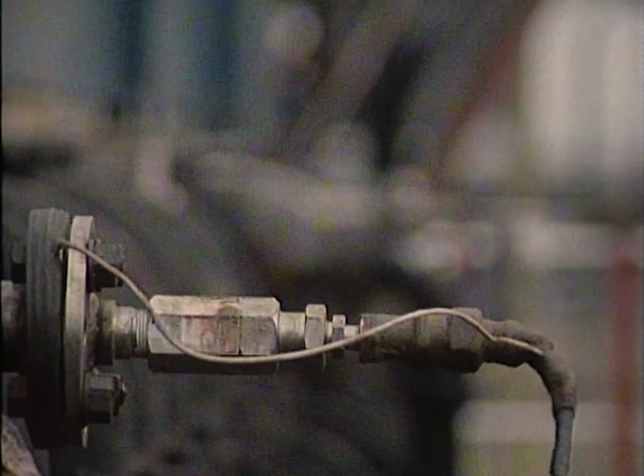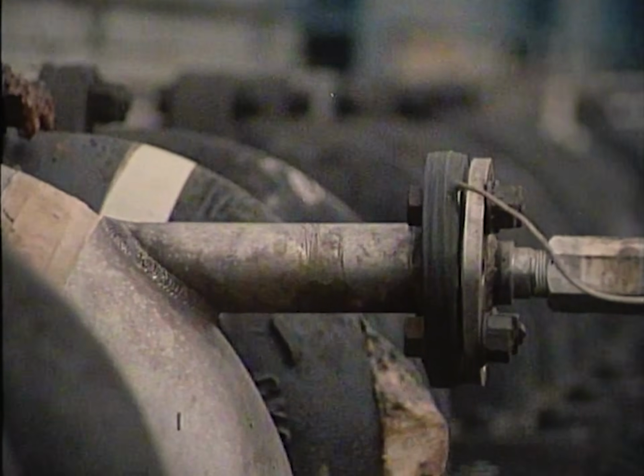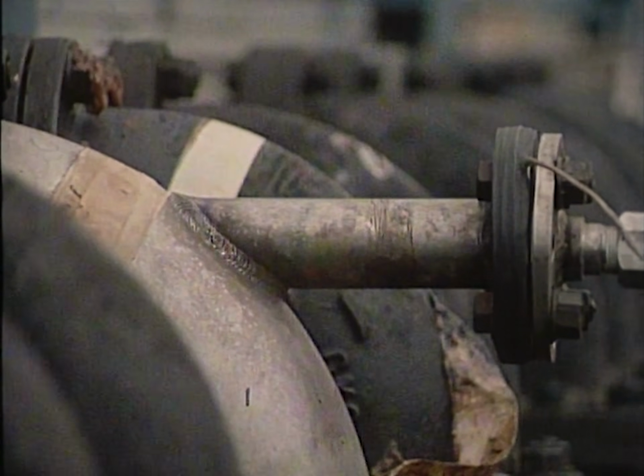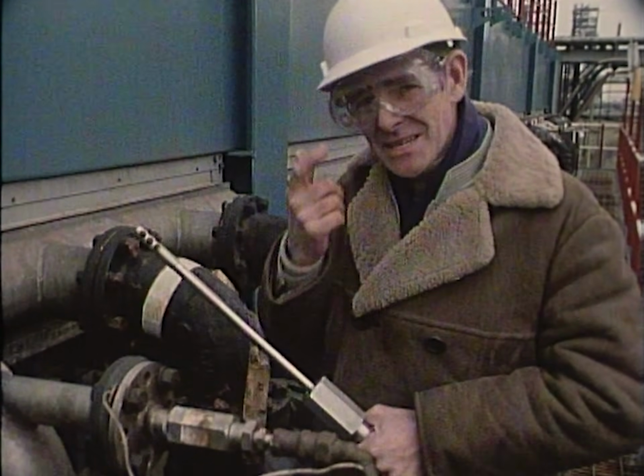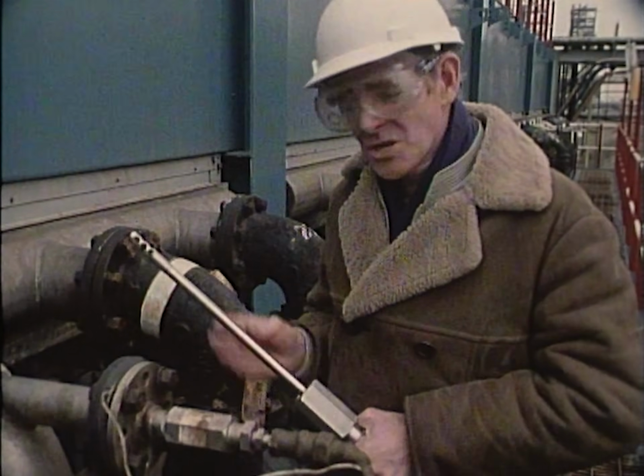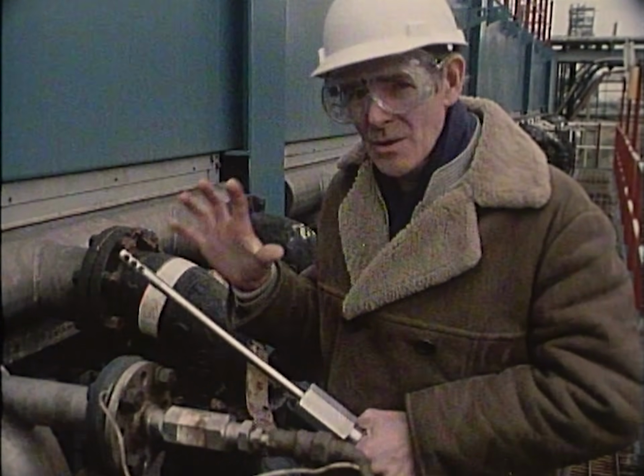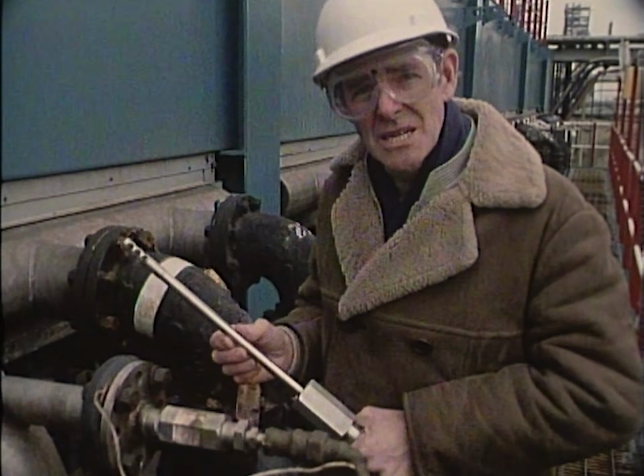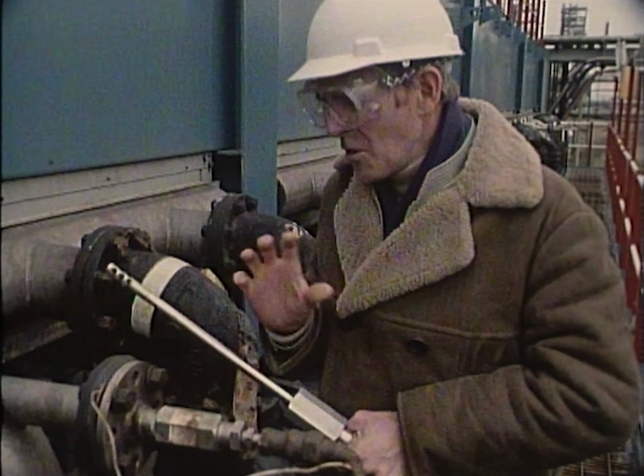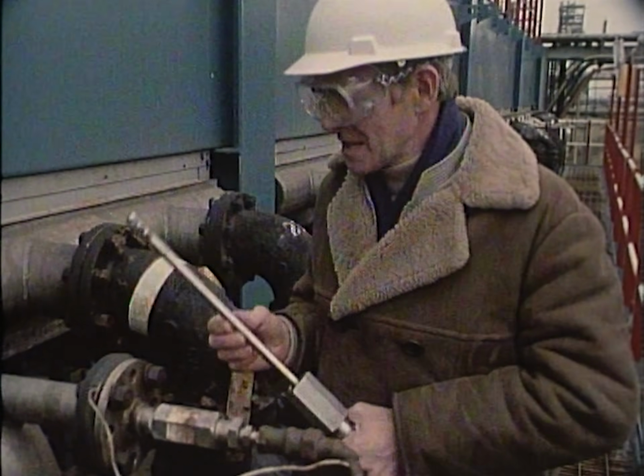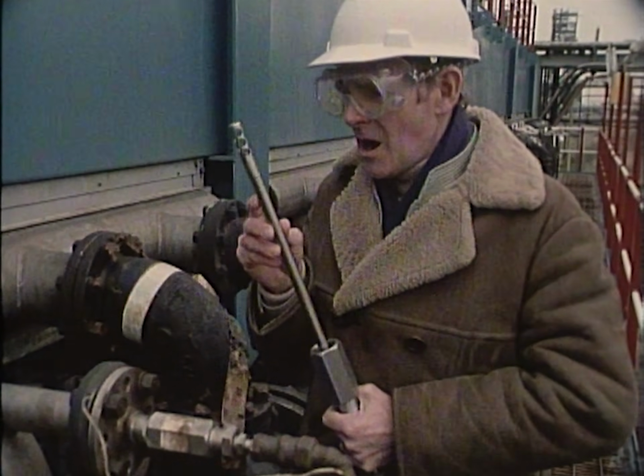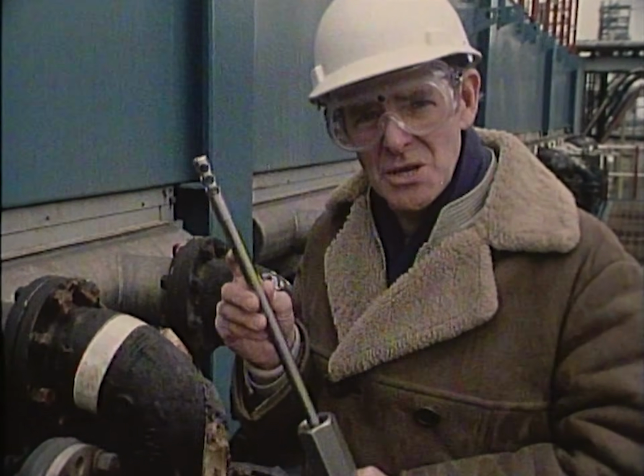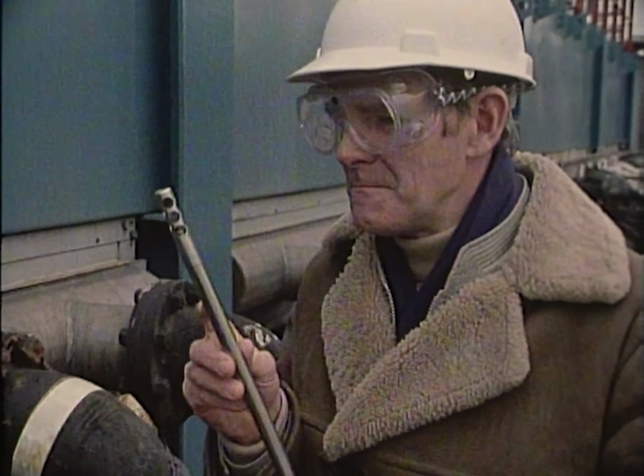This plant has sulfuric acid running through these pipes at a rate of 1,200 tons an hour. It's 98% pure at a temperature of 75 degrees centigrade. Hence the need for the goggles. Hence also the need to know exactly what is happening in this plant in terms of corrosion. Now, fortunately, there are ways of measuring that, and this is typical of the sort of probe that is used under this kind of condition.